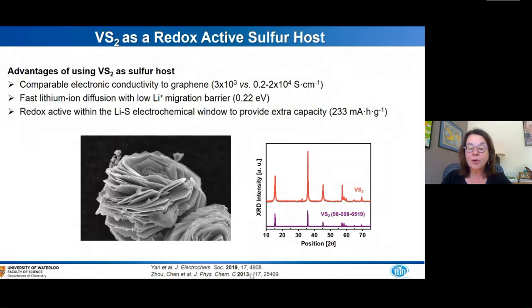This is reported in these papers cited down below. Particularly interesting is that it's redox active within this lithium-sulfur window, so therefore it provides extra capacity. One can compare these materials as nanoflakes, as shown here with the appropriate diffraction pattern on the right.